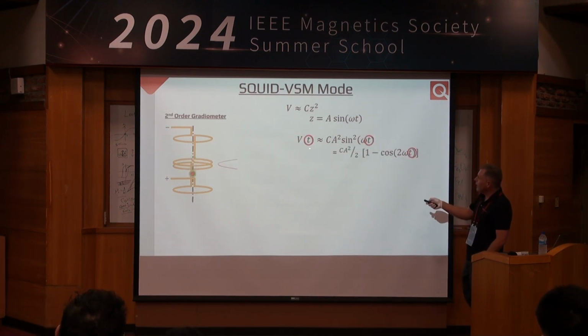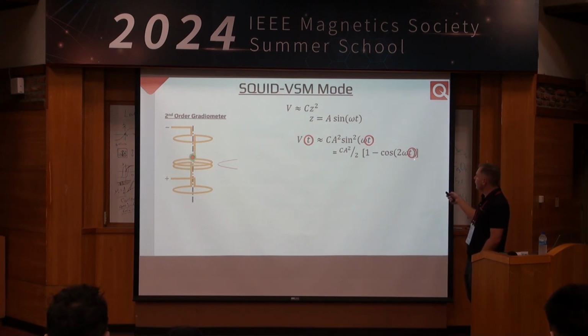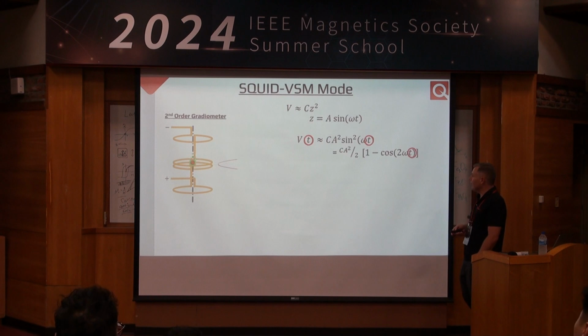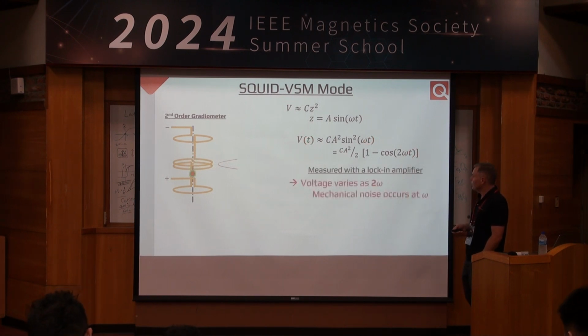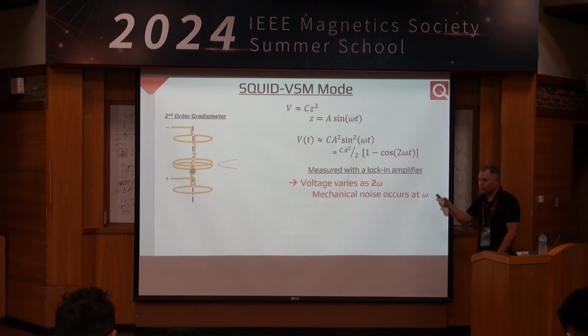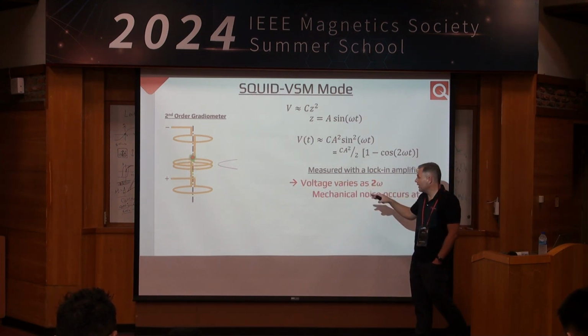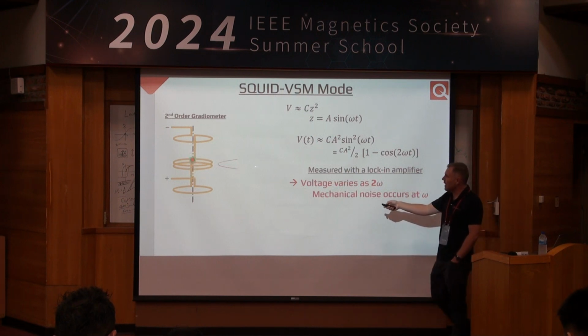So this is interesting. We're now measuring the voltage not as a function of space, but as a function of time. And we're using a lock-in amplifier to do this. Interestingly, the voltage varies at twice the frequency of the oscillation here. So this is very nice. That means mechanical noise primarily occurs at the fundamental frequency at which you drive something. But we're not looking there. We're looking at the second harmonic. And you can see how that goes here.